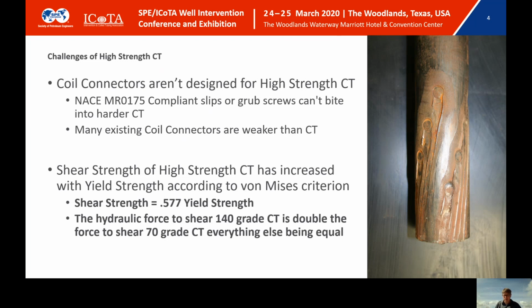BOPs now require more than double the hydraulic force to cut coil than they once did. And the reason it's more than double is because, yes, the shear strength has doubled. The shear strength is a function of yield strength. But the other thing that's changed is the wall thickness has increased significantly as well. It's common to get 130, 140 grade coil in like 175, 204 wall. We've seen 256 wall. These are all things that 10 and 15 years ago weren't thought to be possible.